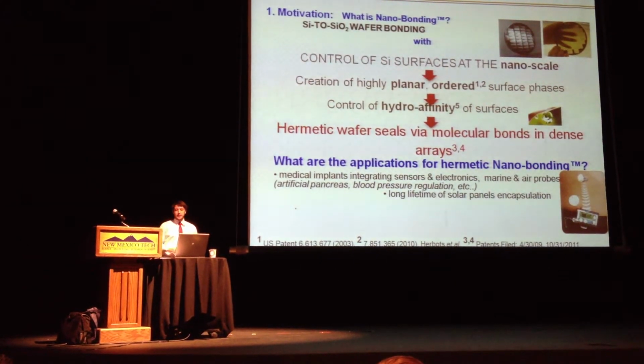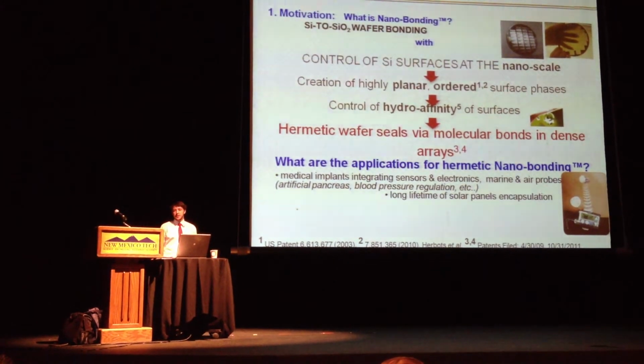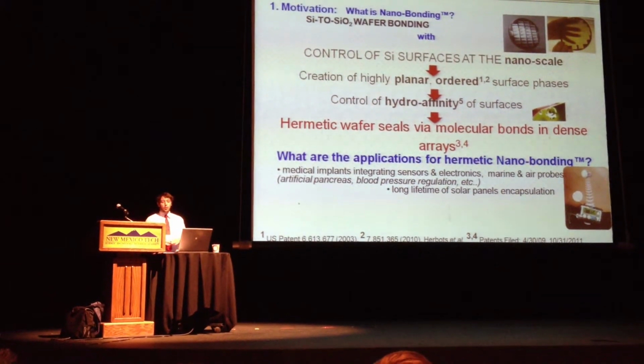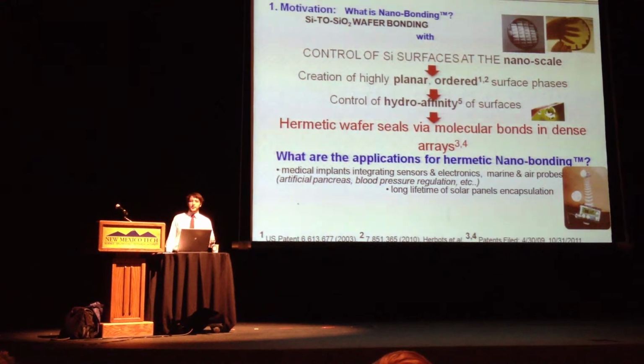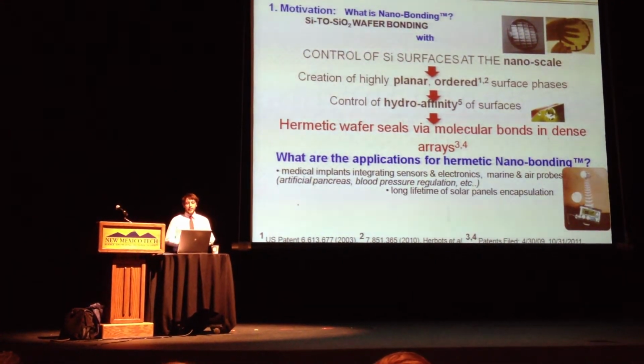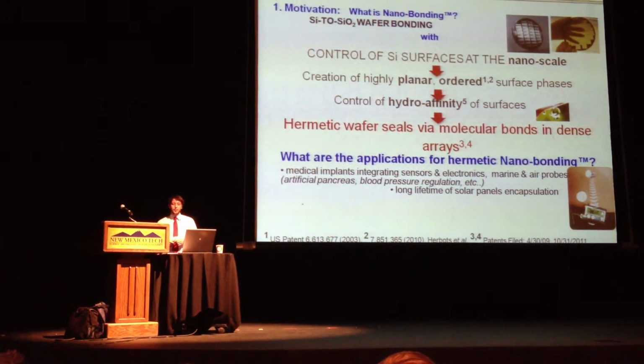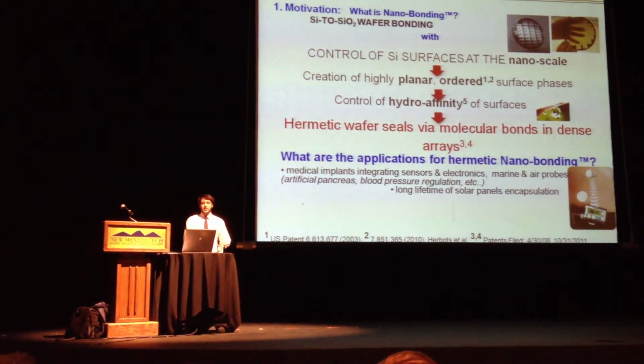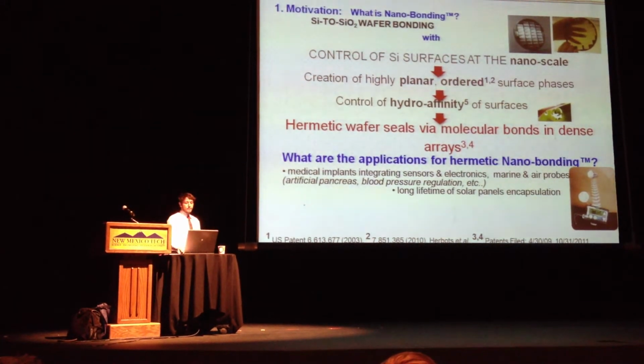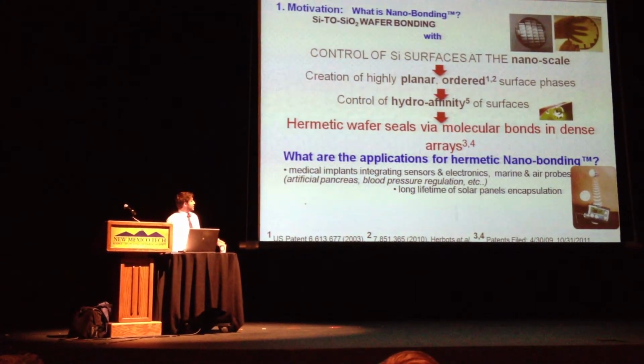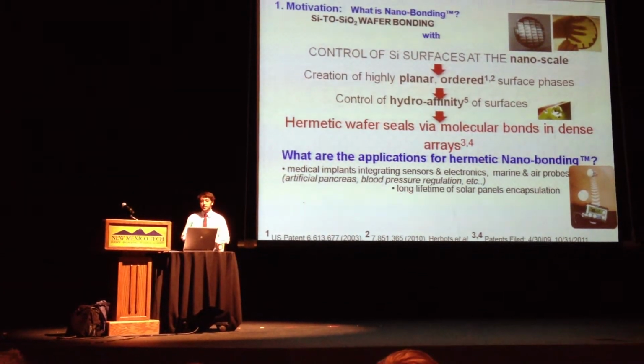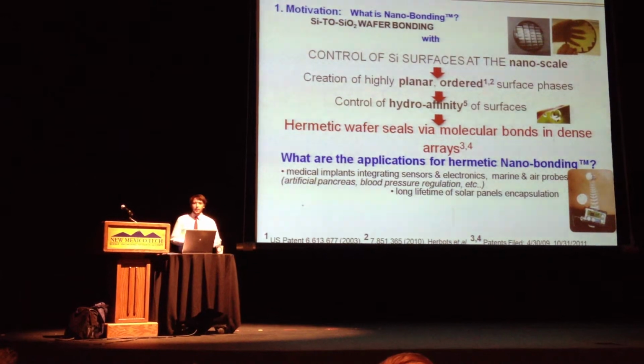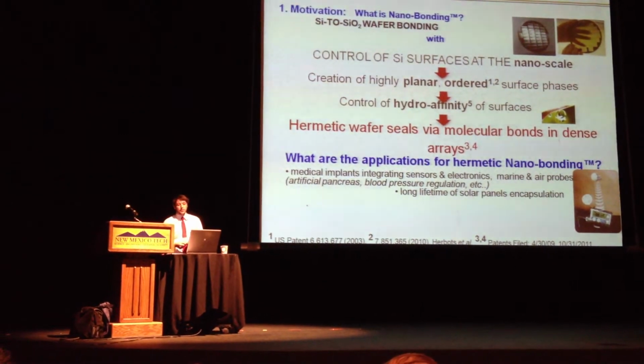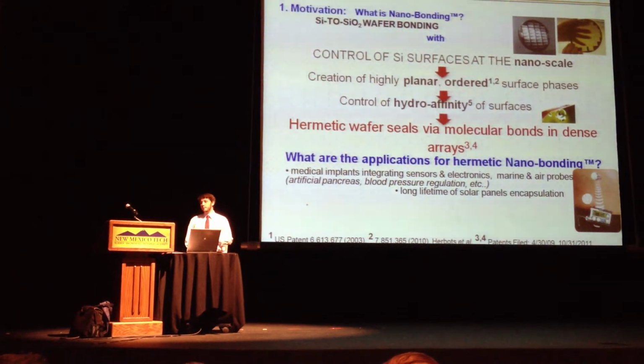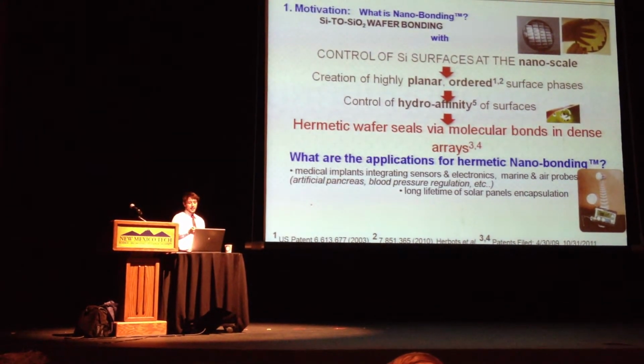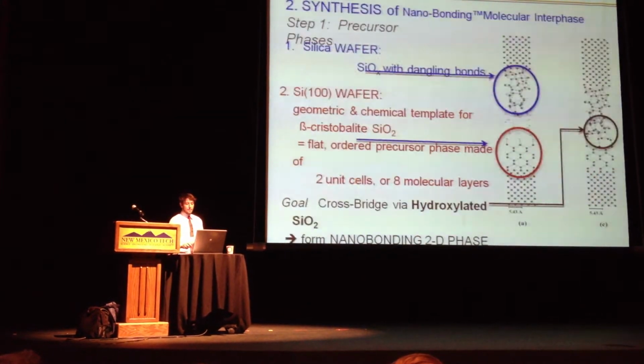So here is the essence of what we're doing. We're controlling the silicon surfaces at the nanoscale, creating highly planar ordered surface phases, so that's the definition of our two-dimensional surface interface, and then controlling the hydroaffinity, and that's a way that we can characterize this, by understanding the hydroaffinity of surfaces. And our goal is to create these hermetic wafer seals via these molecular bonds that occur when we have these conditions met. So this is important in medical implants and then marine or air probes where that hermeticity is going to be important for the lifetime of the device.